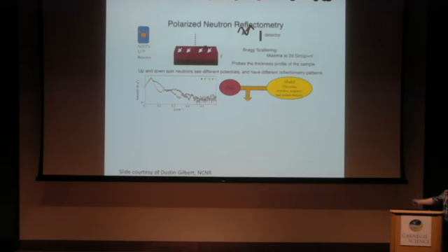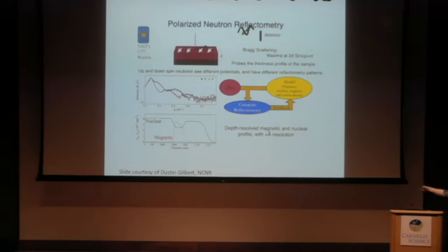So we take this data, we then model it with what we know of the structure from various X-ray or TEM techniques, and from doing the growth ourselves, we know what we think we have. And we can compare this to reflectometry consistently and feed this back into a model until we get something that converges and generates a nuclear profile. So this is the nuclear contrast, and a magnetic profile and the magnetic contrast, and this is an incoherent thing here. And we also can back out the direction of the magnetization with respect to the field we're applying. So in this case, we're actually applying a magnetic field to orient the moment, so we don't have to deal with domain effects. So what you get is depth resolved magnetic and nuclear profile, and you get angstrom resolution here.